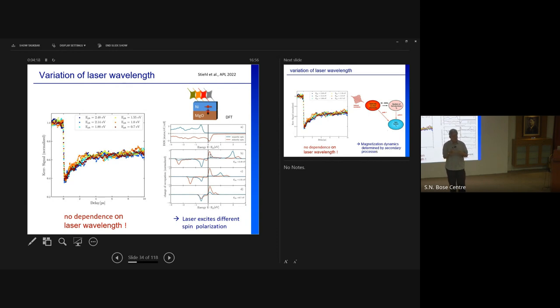I would say, theoretically, yes, for a theoretician, yes. We as experimentalists know that we need a uniform magnetized film. That means we have to deposit a thin cobalt film on gold or whatever. And we know when we heat over 500 degrees, gold starts to penetrate into the cobalt film. So that can then be the limiting factor, something like that.